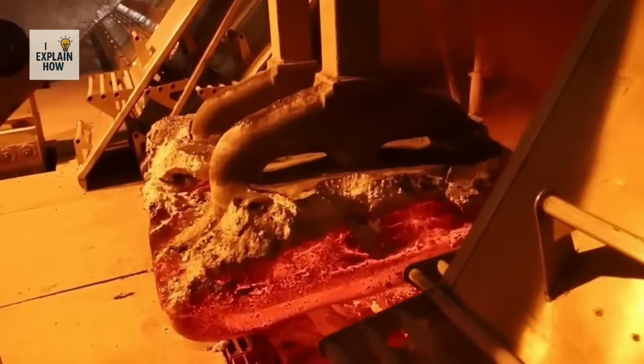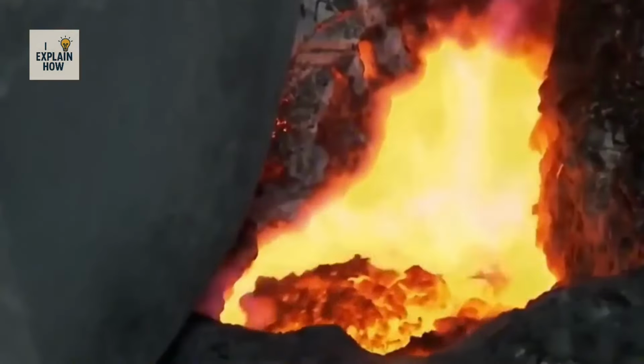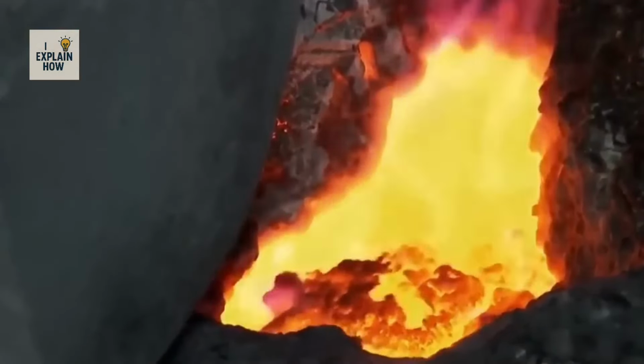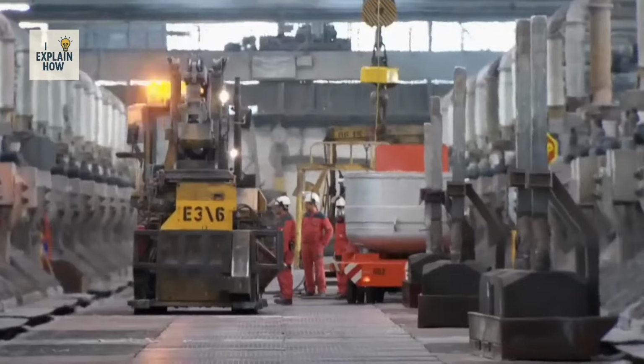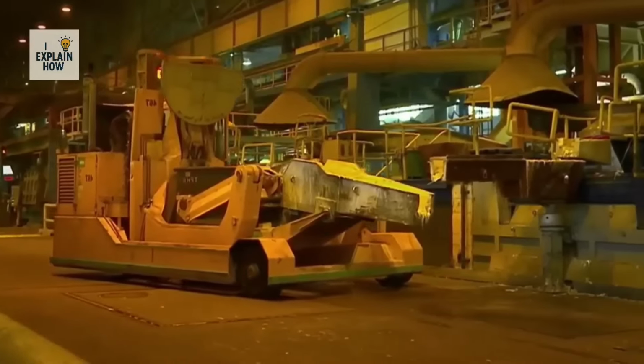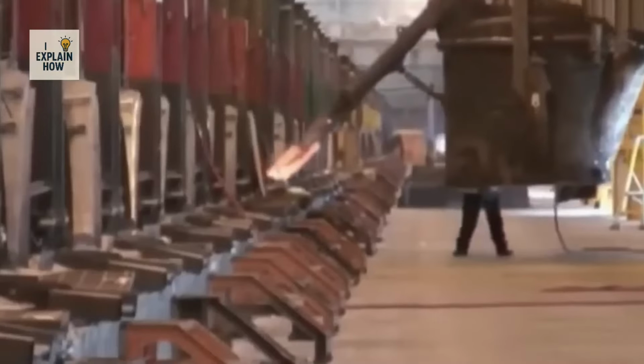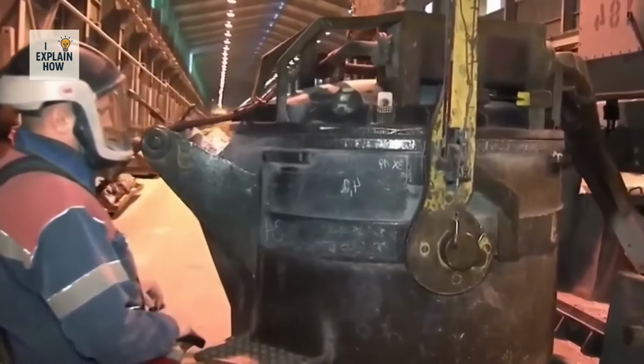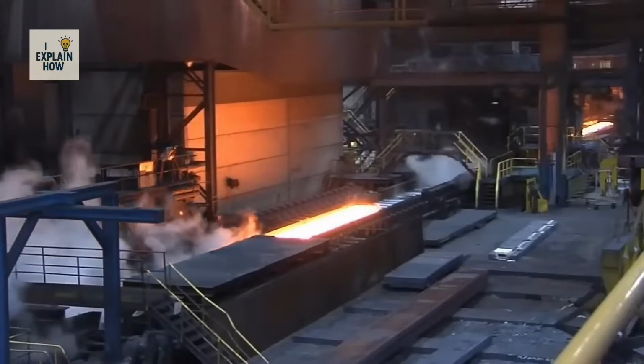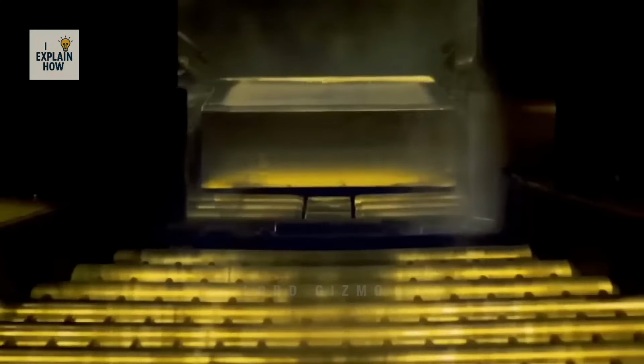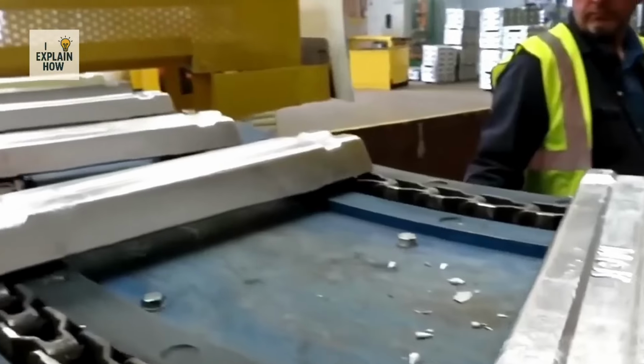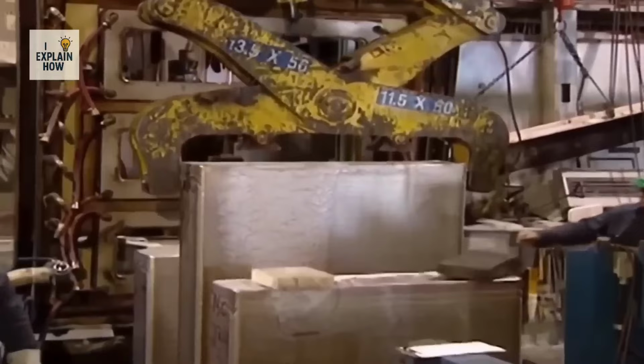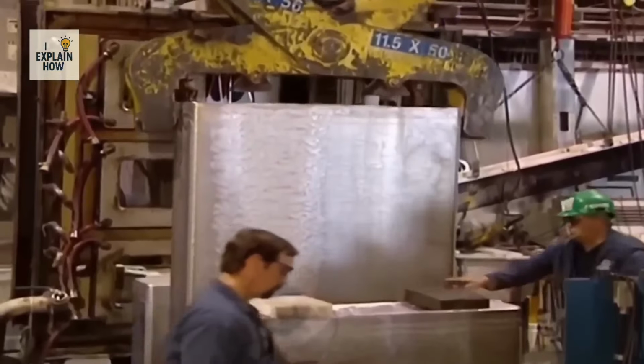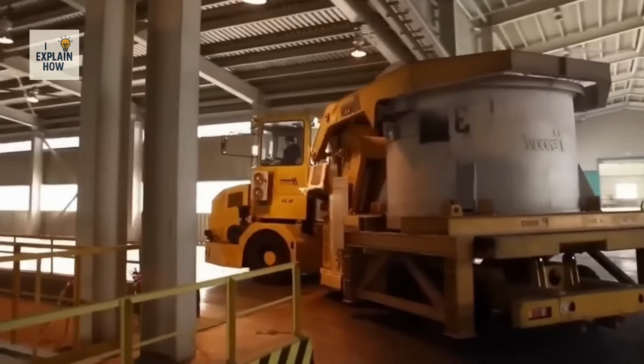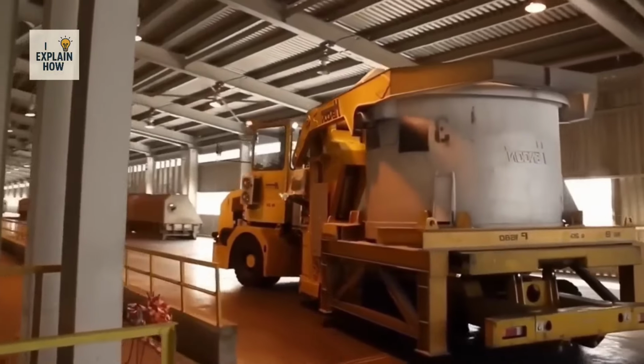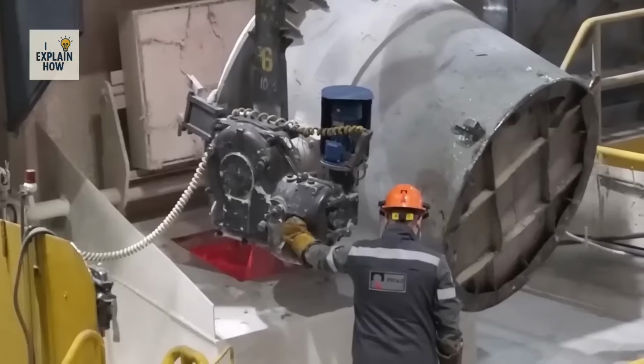The aluminum oxide molecules they contain are composed of 2 aluminum atoms and 3 oxygen atoms. The electric current breaks these bonds, separating the atoms. The oxygen rises to the surface of the container and reacts with the carbon anodes to form carbon dioxide, while the denser aluminum sinks to the bottom. After electrolysis, the molten aluminum at about 950 degrees Celsius is separated from the cryolite by suction pumping. This process takes place in continuous cycles every 36 hours to extract the metal from the cells.